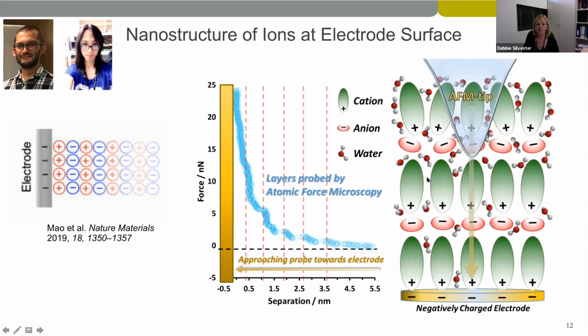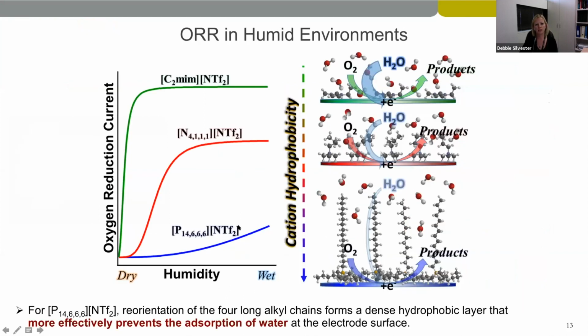But when we have water present, in some of the ionic liquids we see a force curve which doesn't have any of these distinct jumps. And so this suggests that the layering of the ions at the electrode has been disrupted by the presence of water. And so we chose 3 extreme cases.